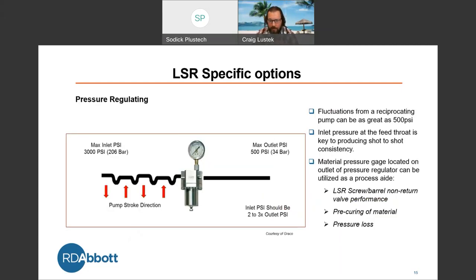The pressure regulation, this is where we want to isolate those pump strokes. So in the direction of your pump stroke, you have high and low pressures. We want those fluctuations to be flat. We want our inlet pressure to be a nice smooth flow. This allows us to get a consistent fill. And looking at this, with this regulator and the gauge, it shows us performance of our non-return valve.